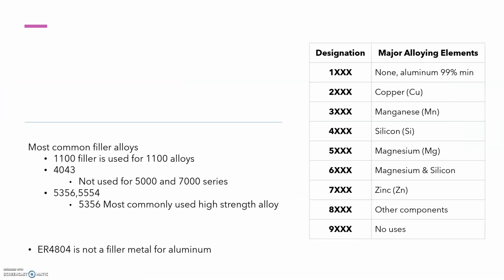Most common filler alloys are 4043 and 5356. 4043 has 5% silicon added, which makes it softer and easier to feed. If surface temperatures are high, 4043 is your best choice and is less crack sensitive. 5356 has 5% magnesium added, which increases the strength, but will not stand up to high temperatures.